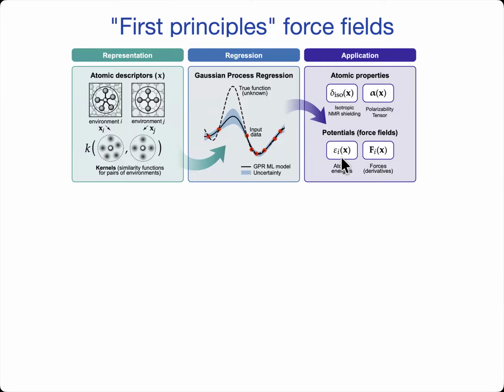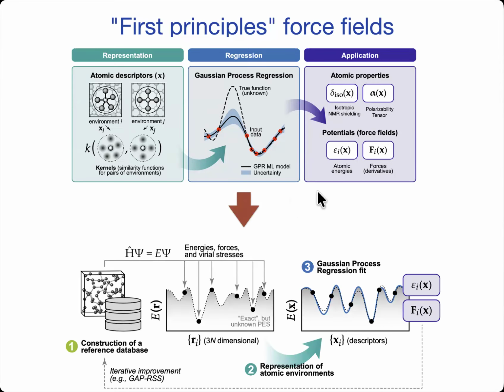So you regress the atomic energy and the forces that you compute with electronic structure theory. So you need data to do this regression. You do electronic structure simulations on a size scale where those are feasible, because of the much worse than linear scaling. Depending on the method, this could be dozens of atoms or hundreds of atoms in the case of DFT, for example. And then that gives you points on the potential energy surface. And with your representation and regression, you essentially come up with an interpolant of the potential energy surface, which you can go and test and validate extensively. And if it's good enough, you use it. If it's not, you go back and get more data.